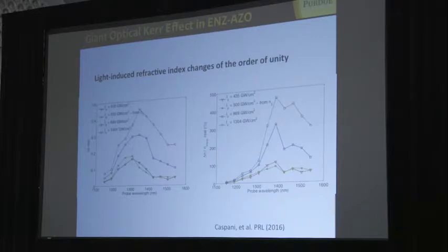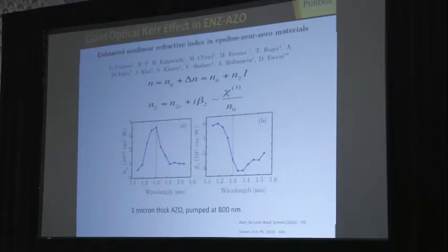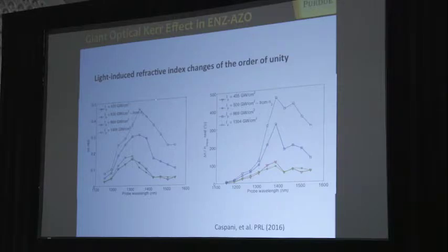You could also look at this nonlinear term delta n, and delta n in this case could be significantly larger than n naught. In our case, it's like 0.4. Of course, it depends on intensity, it's proportional to intensity, whereas the linear refractive index is significantly smaller. So if we look at the ratio, delta n over n, it's actually like 5 times larger. I mean, the nonlinear term is 5 times larger than the linear one.